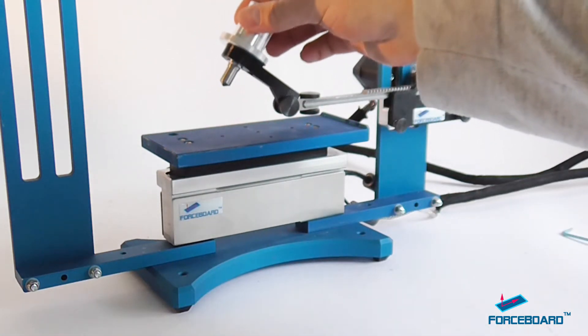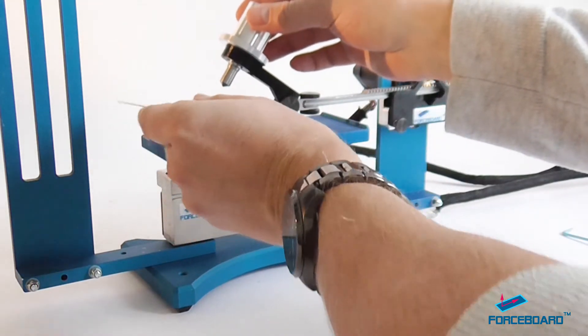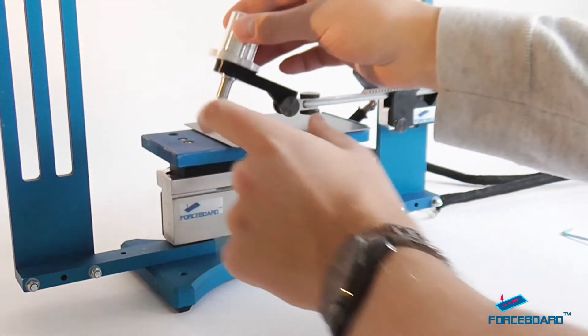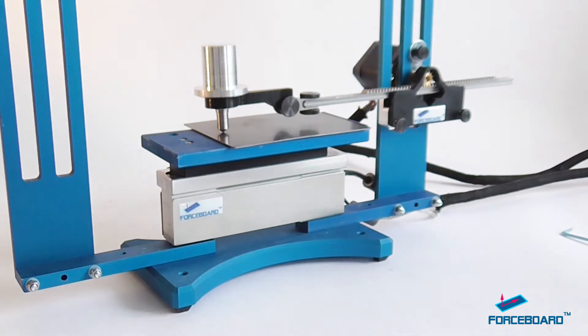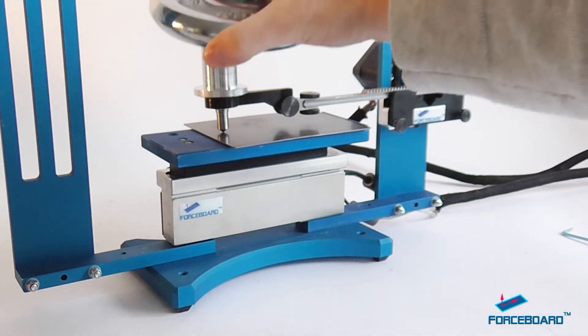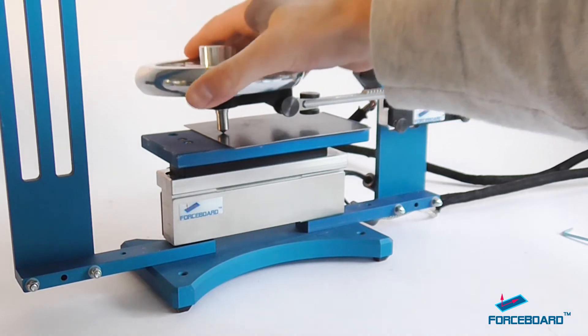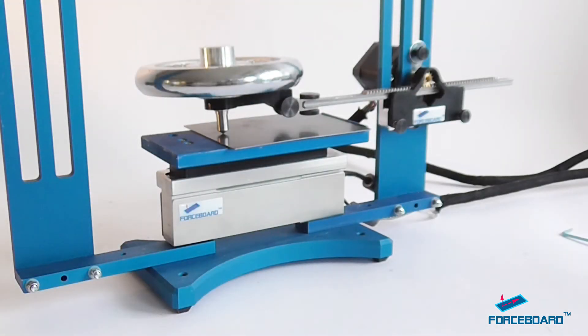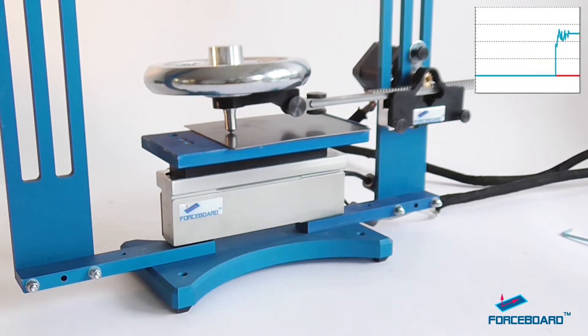The second test object is a coated metal plate. We are using a weight of 1.25 kilograms, which is roughly around 2.7 pounds. We tell the software to move our diamond probe 40 millimeters with a speed of 10 millimeters per second.